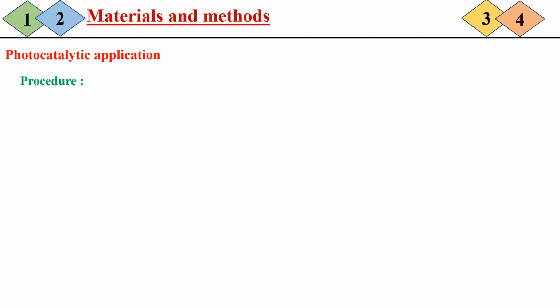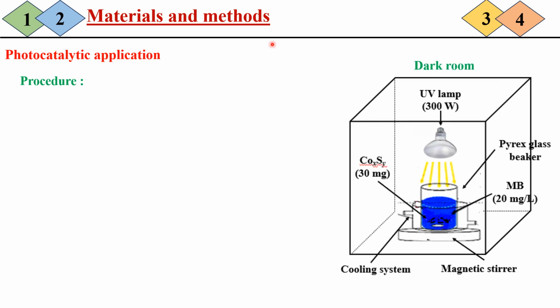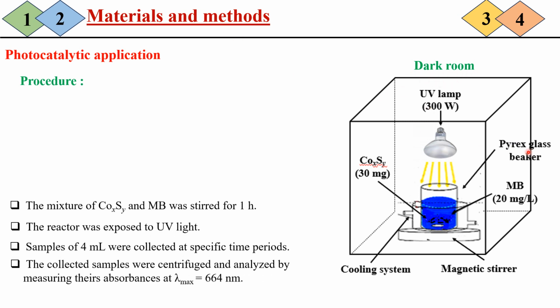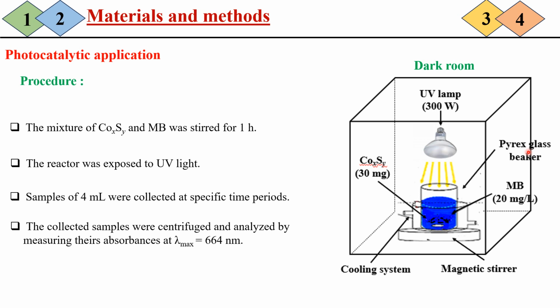After getting the suitable materials, we applied them as a photocatalyst. The process was carried out in a dark room. Firstly, we mixed our materials with an MB solution and stirred them for 1 hour. After that, the reactor was exposed to UV light. Then, 4 samples of 4 milliliters were collected at specific time periods to be centrifuged and analyzed by measuring their absorbance at lambda max equal to 664 nanometers.